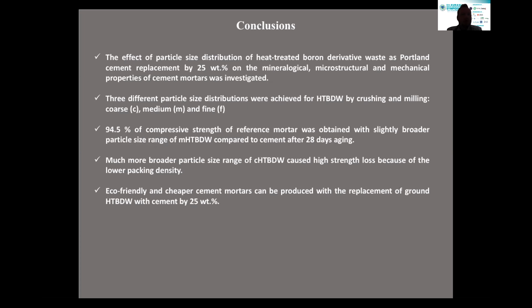A much broader particle size caused the strength loss because of the lower packing density, but it should be noticed that eco-friendly and cheaper cement mortars can be produced with the replacement of ground heat-treated wastes with cement, with the replacement of cement by 25 weight percentage.